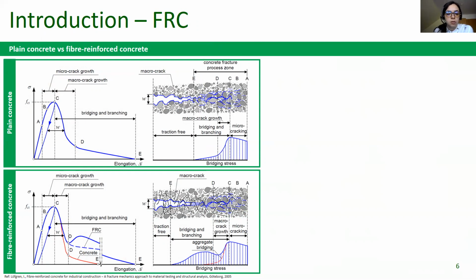However, in fiber-reinforced concrete, the bridging capacity of the aggregates is widely improved by the incorporation of fibers, which can bridge and branch the crack, improving the fracture energy and the toughness of the material.